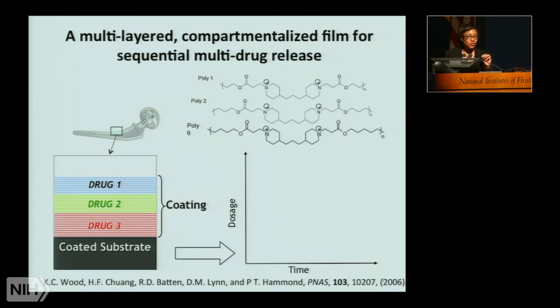This means that we can get a huge amount of the drug into a very small film. And this film is small enough, thin enough that it can coat a range of different substrates and fairly complex geometries. On top of that, we can pair each drug with a different polymer and get a different release rate.